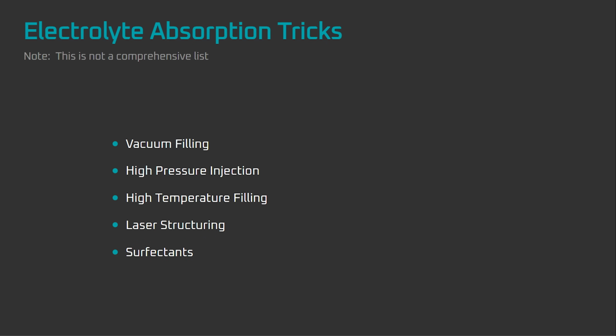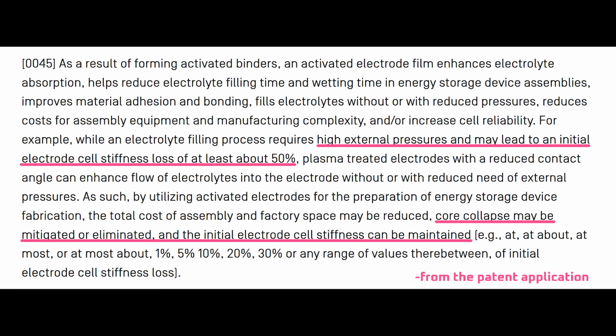To avoid that, manufacturers use a variety of tricks to accelerate the absorption of the electrolyte, such as creating a vacuum in the cell before injecting the electrolyte with high external pressure, high temperature filling, laser structuring to create capillary channels, and surfactants to reduce the surface tension of the electrolyte. All of those come with disadvantages. For example, placing the cell under vacuum and then extreme pressure can reduce the stiffness of the electrode by about 50%. That, in turn, can cause the tight inner spiral of the battery cell to unwind, or in the words of the patent application, collapse.